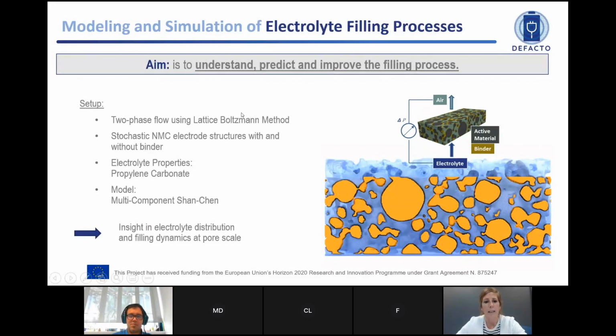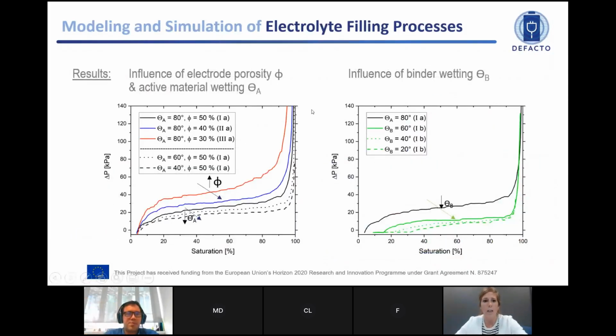But what is shown here is based on the 2-phase flow using the lattice Boltzmann method. Basically, virtual electrodes are configured, and these electrodes take into account the active material with and without the binder. For this setup, the electrolyte properties mimic the propylene carbonate parameters, and the model itself is based on the Shan-Chen approach. Basically, we want to evaluate the pressure gradient and also the saturation percentage, depending on certain parameters like the porosity, wetting behavior, and so on. So these are some of the results we have obtained within the factory.